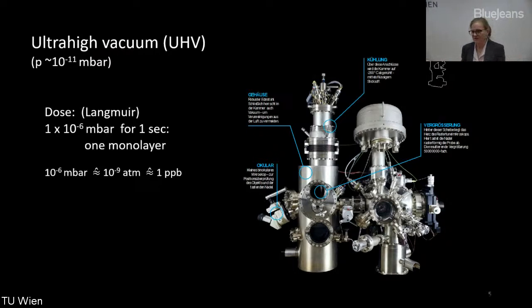What I teach my students in the very first lecture of my surface science class is the dose of 1 Langmuir. If you expose a very sticky surface for 1 second to a gas pressure of 10 to the minus 6 millibar, it's completely covered with a full monolayer. And 10 to the minus 6 millibar is 10 to the minus 9 atmospheres, or 1 ppb, so that's not very much. Normally surfaces are just dirty outside in air, and by putting them in this ultra-high vacuum chamber, you can keep them clean and really study the surface itself rather than the dirt that's on it.